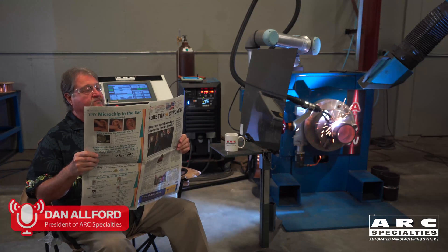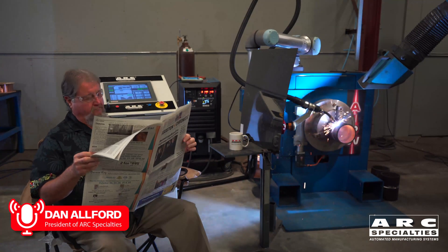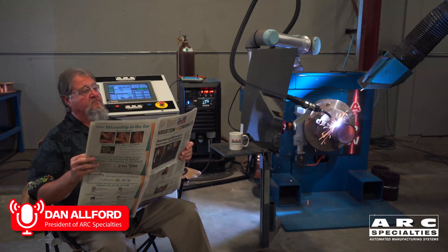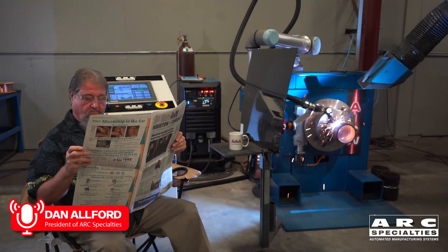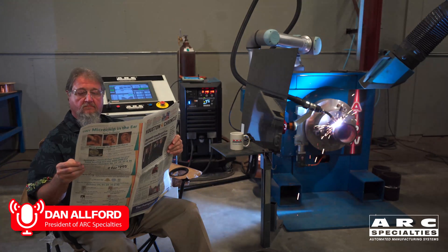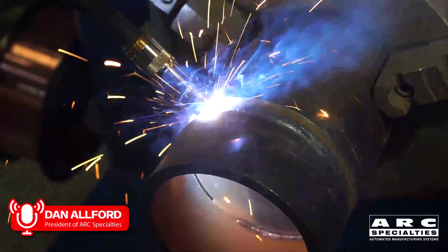And we're welding! The real challenge in automating full penetration single-sided V-groove welds is the variation in joints. We've found that using a collaborative robot, artificial intelligence, and Miller RMD welding, we're able to compensate for a huge range of these variables. We can handle high-low up to 3/32nd of an inch, and we can handle any gap from 1/16th to 3/16th of an inch without any human intervention.